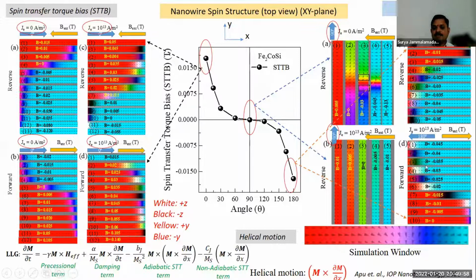The similar thing happened on the negative side, the negative exchange bias phenomena. It is because we have changed the current direction in the opposite direction, that leads to the negative exchange bias. Okay, so as you could see here in this image, such kind of motion of the domain wall attains the helical motion, which leads to the domain wall resistance for the nanowire. So what I would like to convey is that because of this non-adiabatic spin transfer torque term, the domain wall would attain the helical motion, and leads to the domain wall resistance that gives us the spin transfer torque bias in the system. As you could see here, at 90 degrees, we don't see any exchange bias phenomena, spin transfer torque bias over here, because of the coherent rotation of the domain wall at 90 degrees. We don't see anything over there, which exactly matches with our simulations.